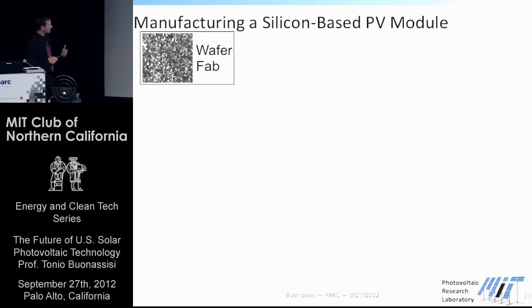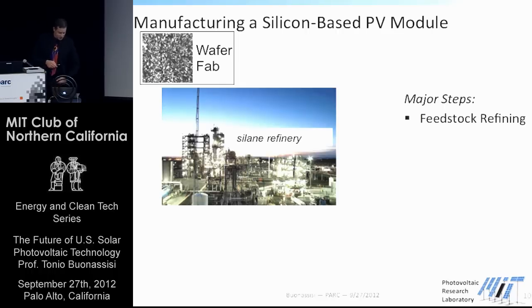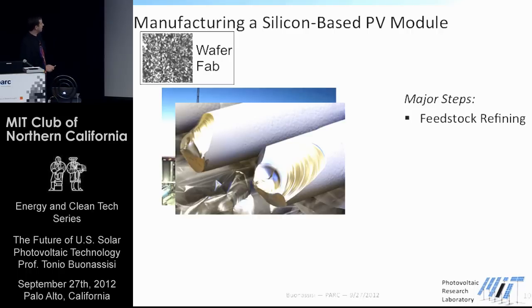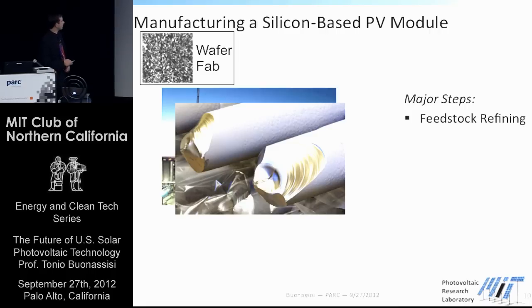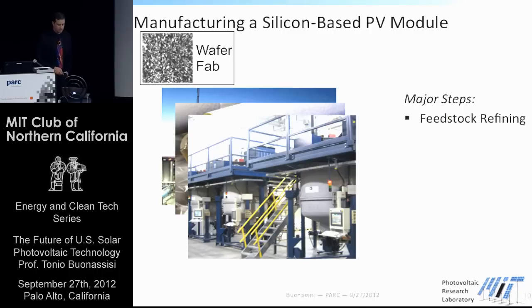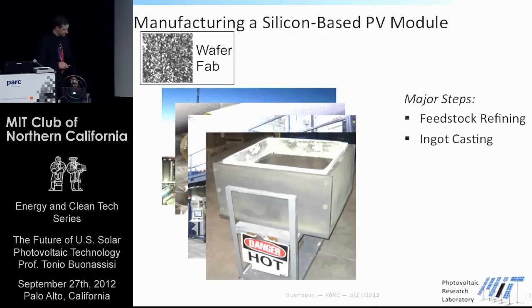So we start out with this mined material, and we refine it into a very, very pure state, a distillation process, in principle similar to how alcohol is refined. We then take that gas, crack the gas onto little rods, these rods shown right here in the middle, and they grow very, very big, wide in diameter. And these are some of the purest materials known to humankind. We then melt those very pure materials in a very impure environment, an industrial environment, forming ingots like this.